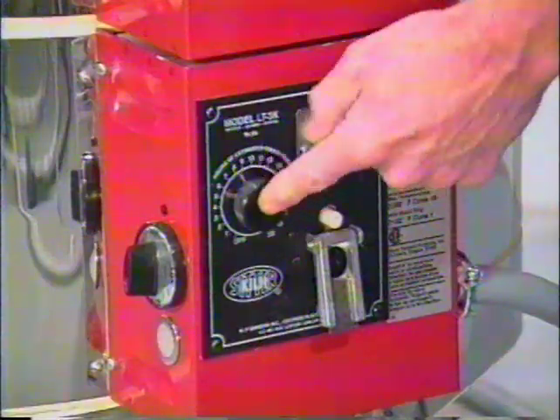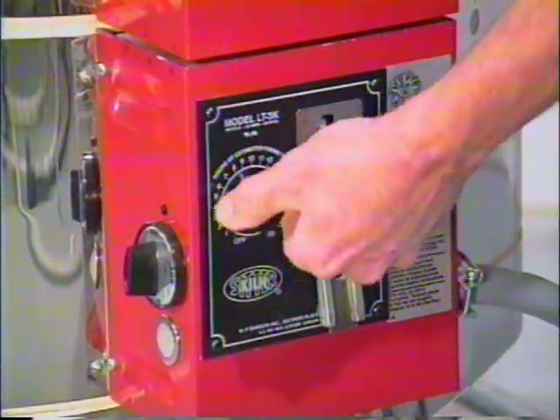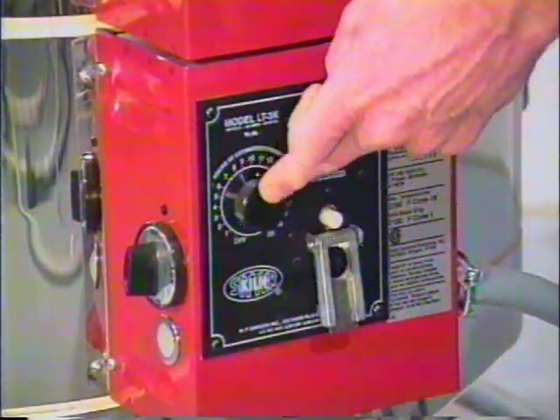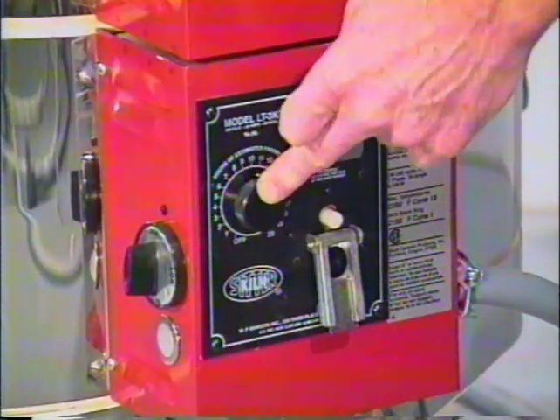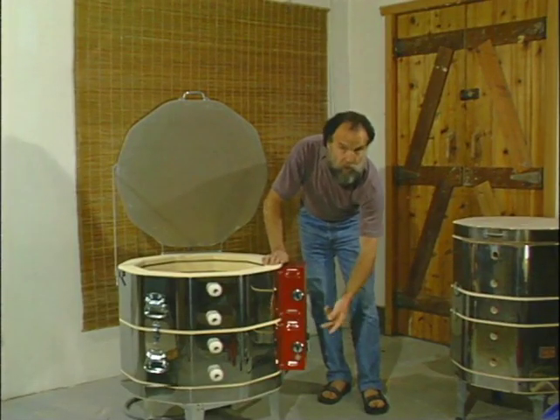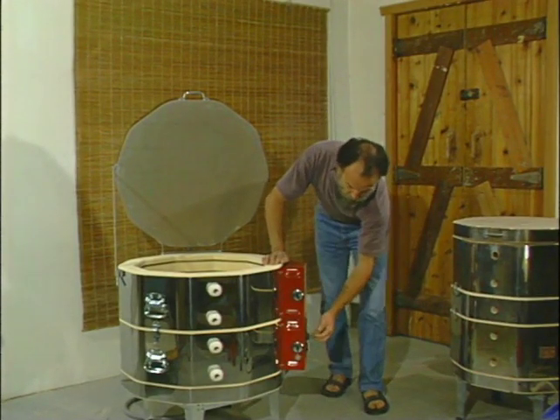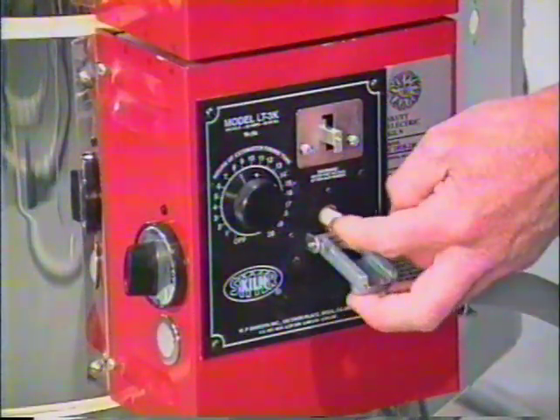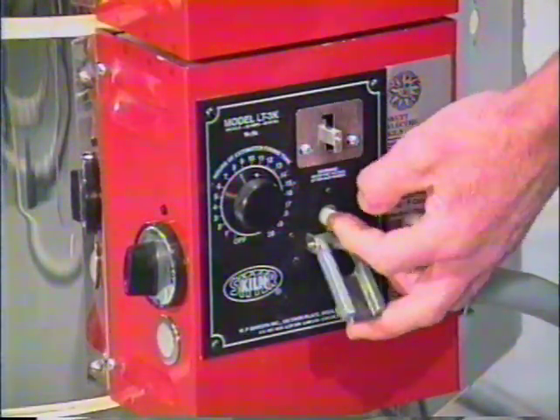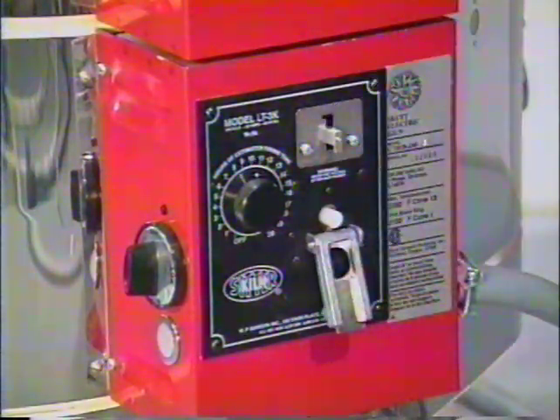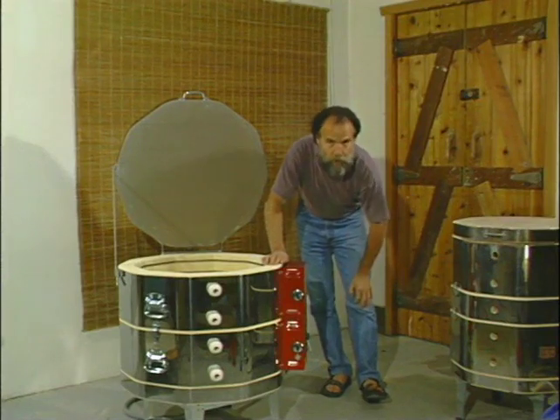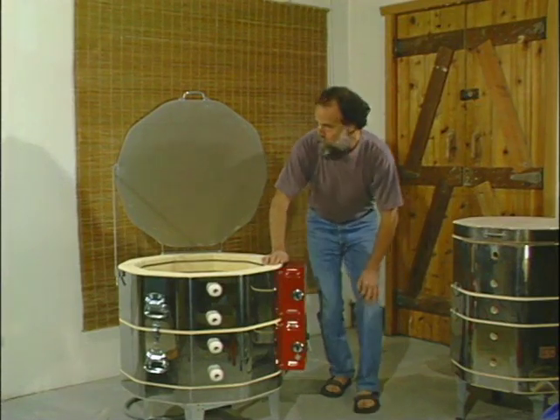Around on the side we have a time switch which you can set to provide an upper limit to the time that the kiln goes so that you don't inadvertently overfire. The kiln sitter is also equipped with a temperature limit switch which you activate with a cone inside the kiln. We'll show you how to do that later when we're loading the kiln.